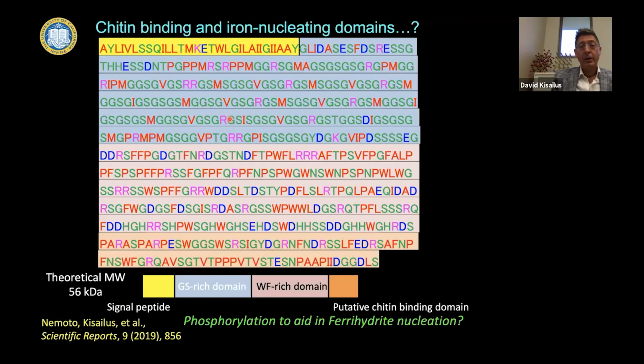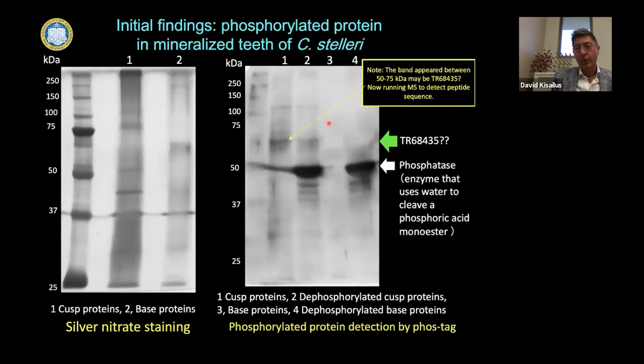We subsequently have gotten the sequence of this protein, where we've identified both a chitin binding domain shown in this orange peach structure, suggesting that this protein is bound to the chitinous fibers. But we also see this serine glycine rich region of the protein. And these serine glycine rich regions are often, via post-translational modification, phosphorylated. And then we speculated that the phosphorylation may be involved in actually nucleating and controlling nucleation of the iron oxides. And that's actually known in human teeth. Actually, there's phosphorylated proteins that actually stabilize some mineral phases. So we've done some dephosphorylation, actually showing that indeed those proteins are phosphorylated.